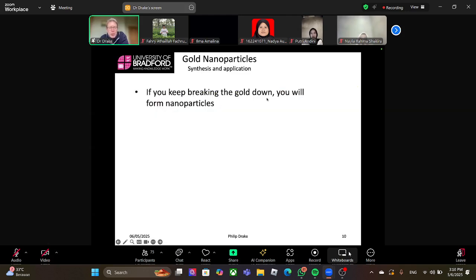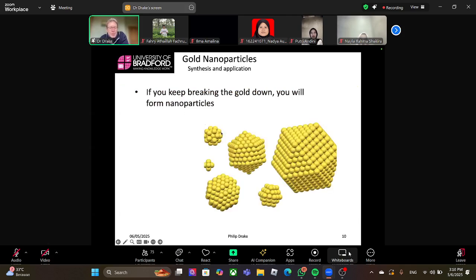If you keep breaking gold down into nanoparticles, you get little clumps of gold. So these are the gold atoms making up gold nanoparticles. We can start off very small. This one here has about 6 atoms. I wouldn't class this as a nanoparticle. I would class this as a gold cluster in chemistry terms. But once we get a bit bigger, we're definitely into the nanoparticle realm. These are no longer clusters, individual atoms. They're metal. Inside, they have metal particles, and they're just lumps of gold.